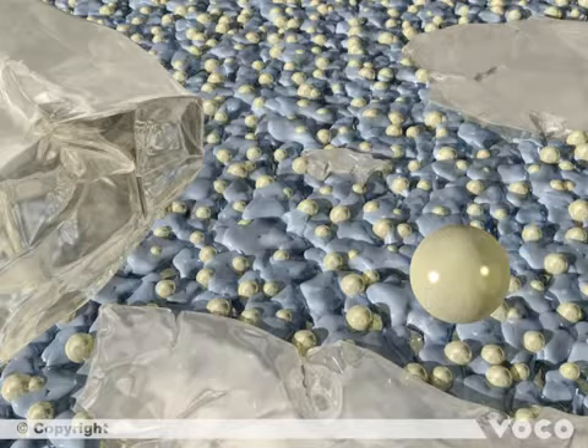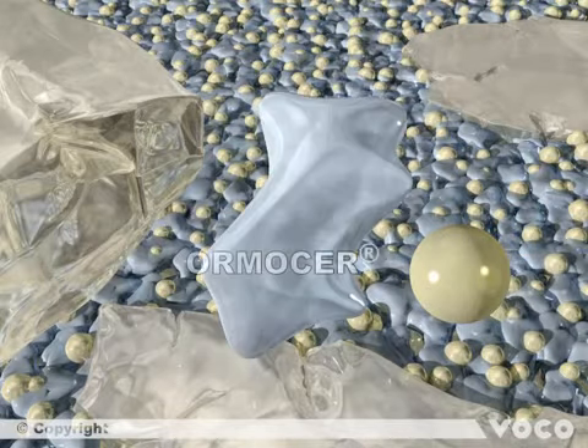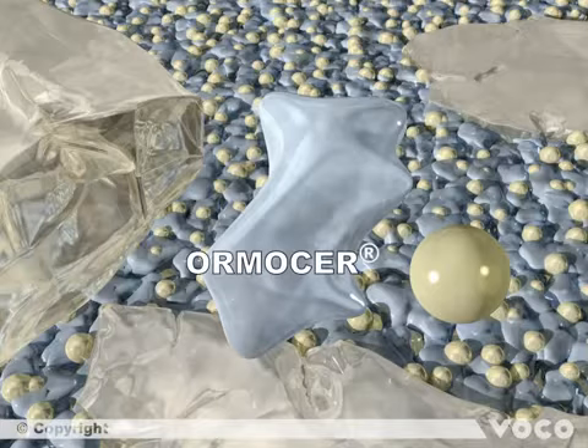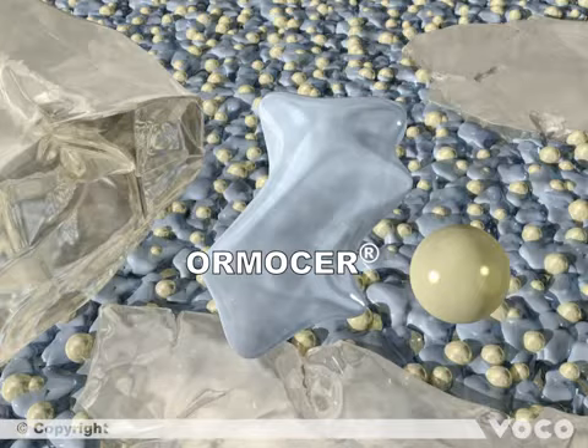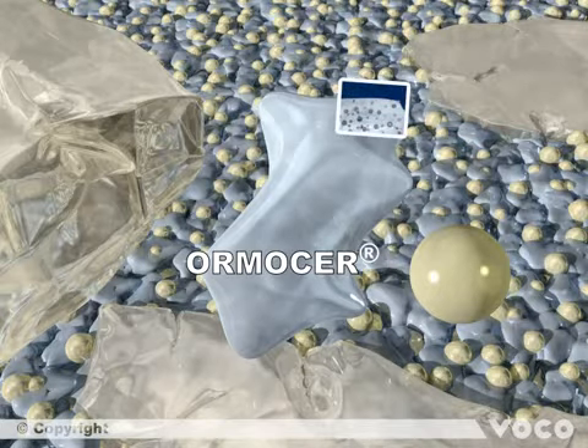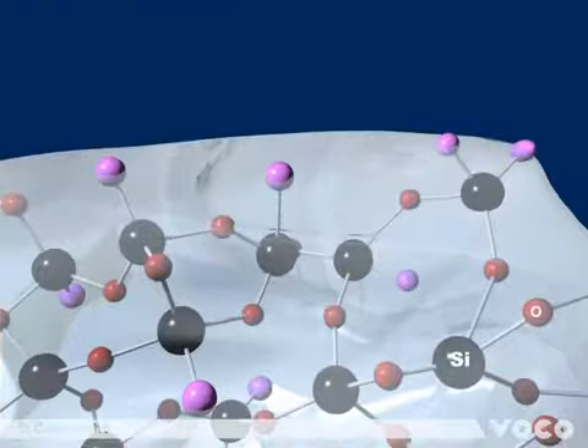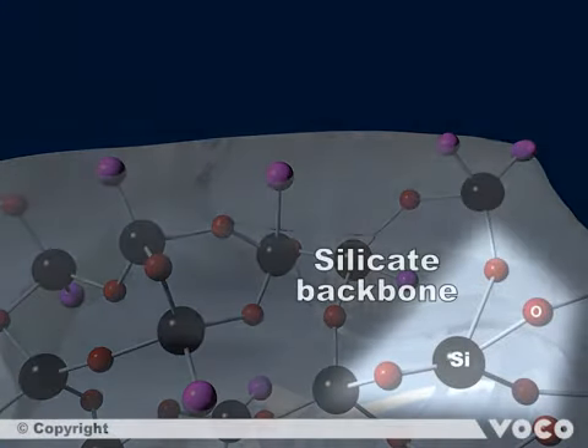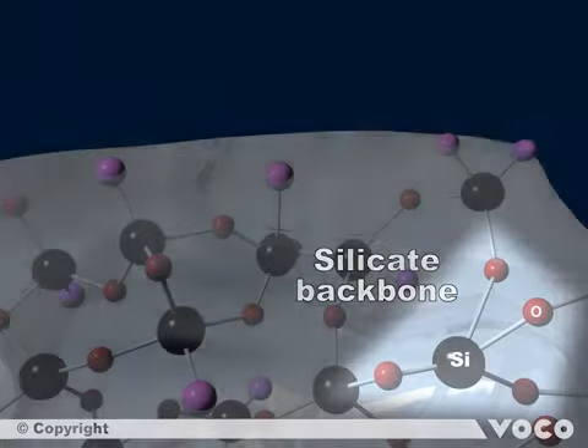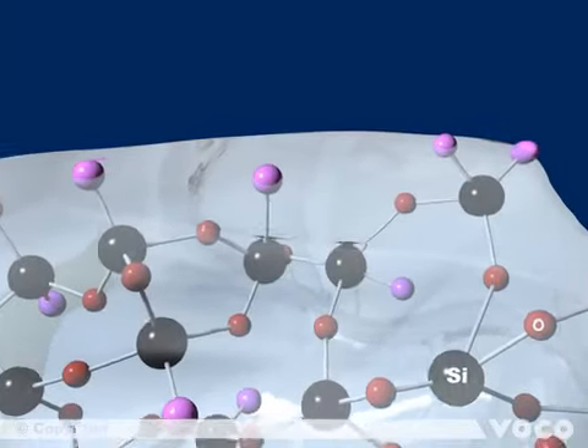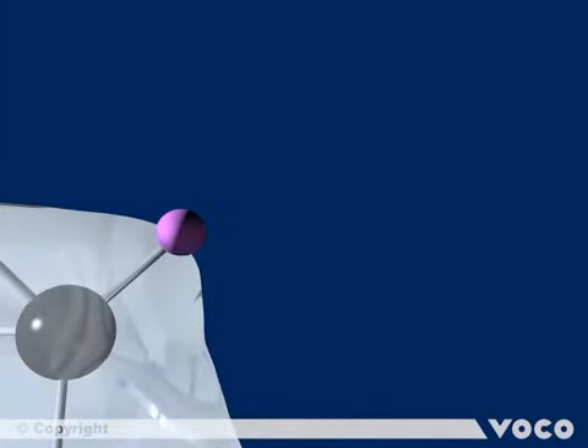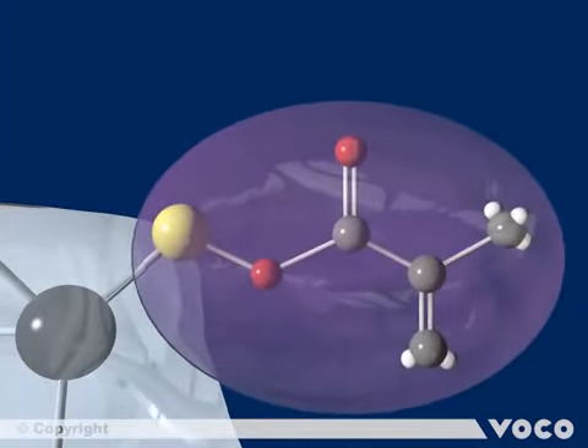The just shown glass particles and nanoparticles are embedded in the ORMOCER resin. After light polymerization, all of the shown matrix elements build up a stable three-dimensional network, in which all the solid particles are immobilized. The unique ORMOCER resin is also based on a silicon oxide network. The silicate backbone of the ORMOCER resin is highly cross-linked. Additional methacrylate groups are contained, which are depicted in purple. The red highlighted double bonds are the linking units to the other matrix elements. The so-called multifunctional ORMOCER resin enables a quantitative fixation inside the polymer network.